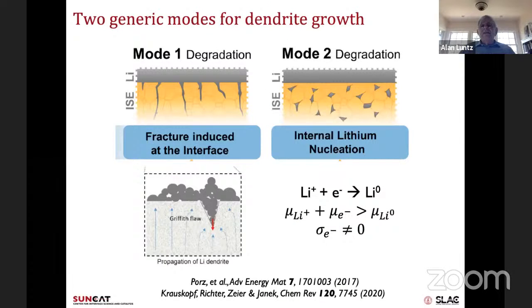Now I want to say a little bit about dendrites, because that's a major issue. Still is a major issue now. It turns out, although because they're stiff they shouldn't allow dendrites to grow through, they do. And there are really two modes for growing dendrites. One seems to be just fracture induced. That occurs whenever you have a defect in the electrolyte, and it starts growing from the tip, and then it gets enough pressure to crack the material. They grow from that either along grain boundaries, which are a little softer, or just through the material. So these are a serious issue. And of course a softer, more malleable, or less brittle electrolyte is better, so it's not as big a problem as it is in the oxides.